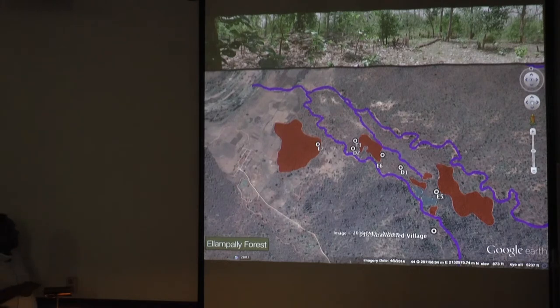And these sites were also very close to clusters of the tree that they used to make charcoal, this tree which they locally call sendra. The sendra tree grows in clusters in the forest, and the smelters knew where the clusters were. They would move from one cluster to the other. They would exploit the cluster completely, and they would let the cluster grow back.